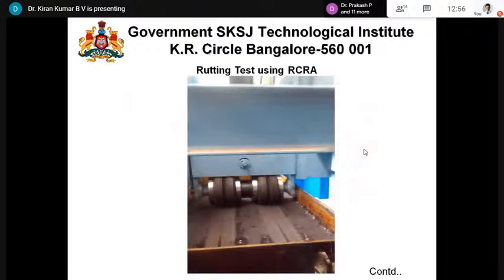Then we have also done a rutting test at our laboratory level with our instrument. These are all different materials we have used at different places and in different videos. Some videos may be repetitive. I have shown them in various forums, but the procedure is: step one, selection of material; step two, job mix formula; step three, compaction, determining the optimum binder content; step four, the moisture content; and step five, the performance evaluation of our new approach.